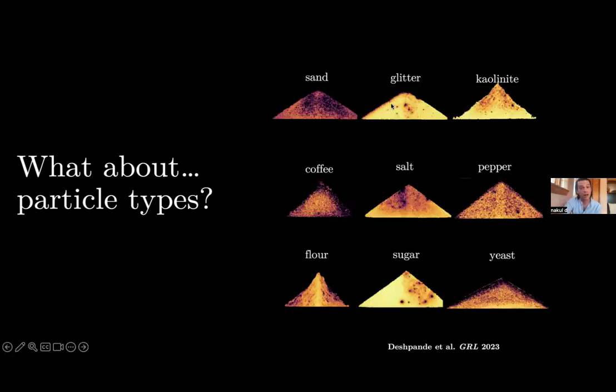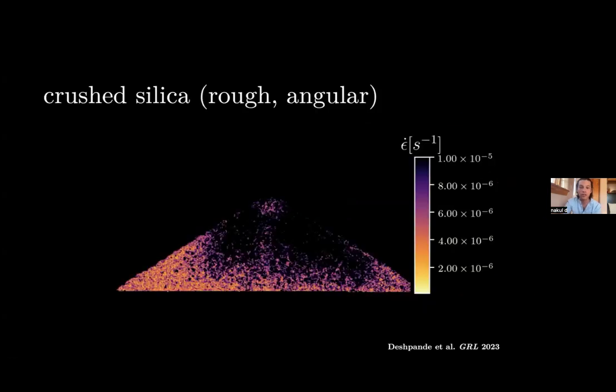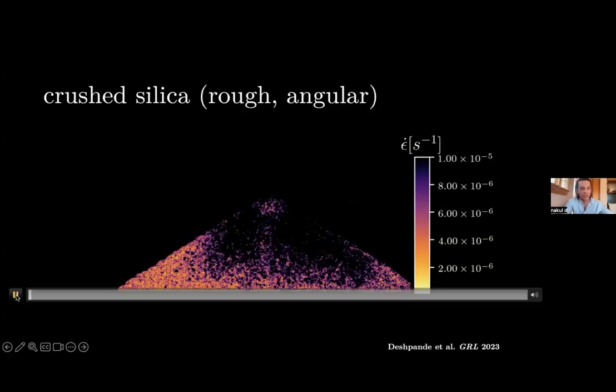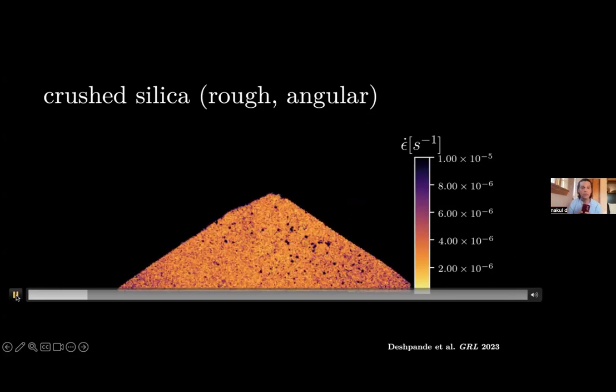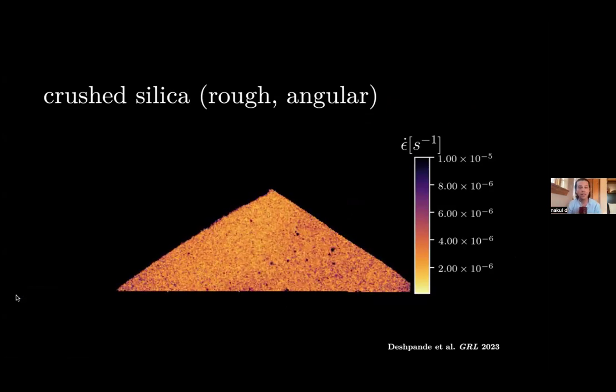And the answer is no, they all creep. You pour them all in the same system, you follow the same protocol of pouring them into a pile, and you observe both relaxation and you observe these discrete zones of deformation that persist even though you're done pouring the pile, okay? So creep is not dependent on the type of material that you use. And just to give you an example, this is crushed silica, right? Where the grains are rough and angular. And these are maps of deformation, animations of deformation that qualitatively show the same behavior as glass beads.